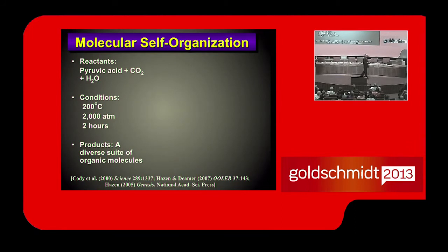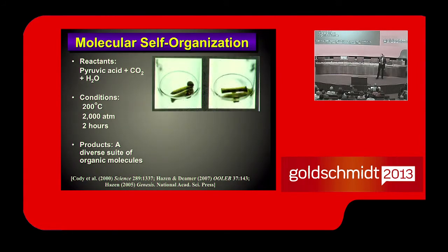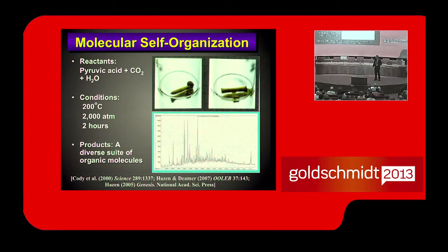One of our early experiments took pyruvate, a 3-carbon molecule, with CO2, put it at high pressure and high temperature, and we were hoping we'd make the 4-carbon molecule oxaloacetate, because that's one of the key steps in a reductive citric acid cycle. But that didn't happen. Instead, we made a yellow-brown oily goo. It was messy. It was smelly. It smelled like Jack Daniels, actually. It was pretty interesting. But when you do the GC of this, you basically see there are thousands of molecules being produced.